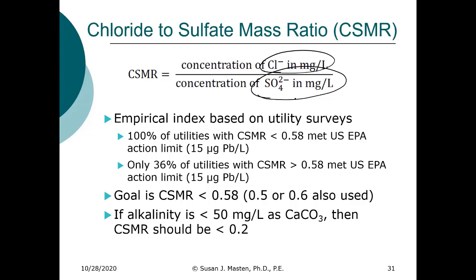And based on an empirical survey of a large number of utilities, what they found was that 100% of utilities that had a CSMR less than 0.58 met this action limit of 15 micrograms of lead per liter. But only 36% met the action limit if their CSMR was greater than 0.58. So it doesn't mean that you will definitely exceed the action limit for lead, but it implies that lead corrosion is more likely to be problematic at a higher CSMR. If your alkalinity is less than 50, then the CSMR should be less than 0.2.